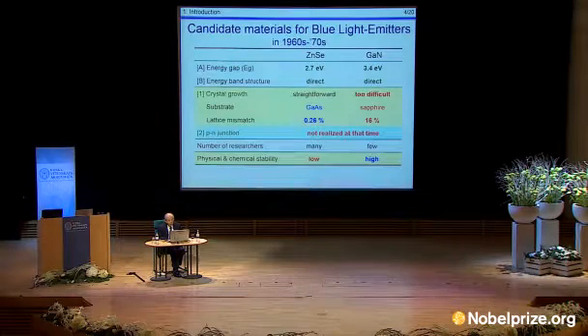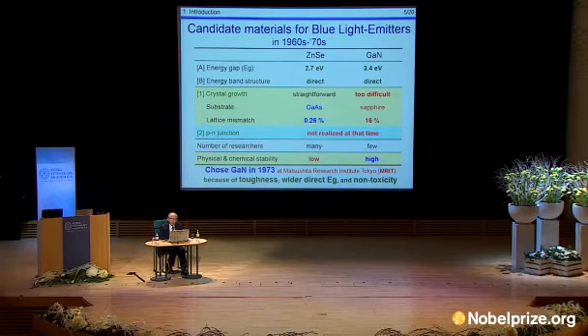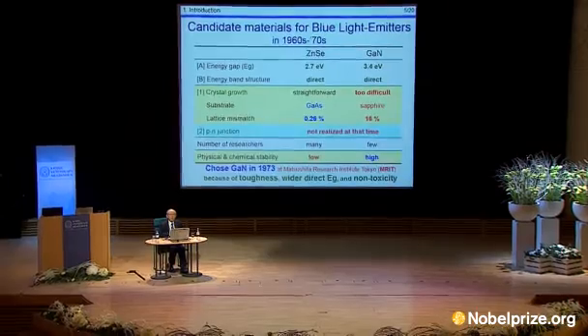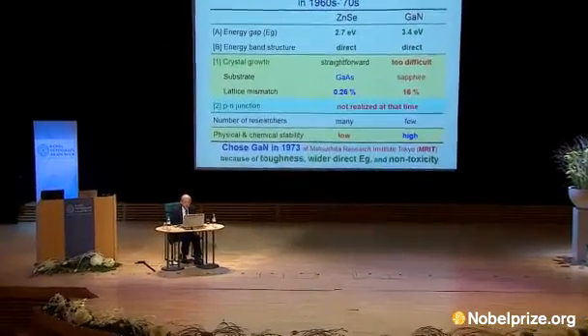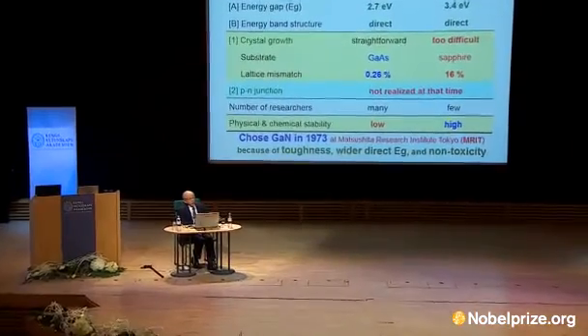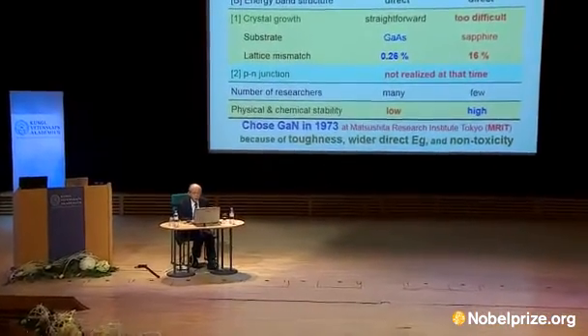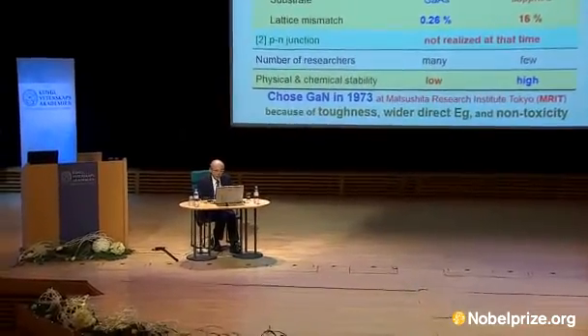I myself, however, worried about the instability of zinc selenide. On the other hand, gallium nitride is far more stable, both physically and chemically. That was a mistype. That is not a p-n junction, but a metal insulator semiconductor structure. But this report accelerated the R&D of nitride-based blue LEDs.